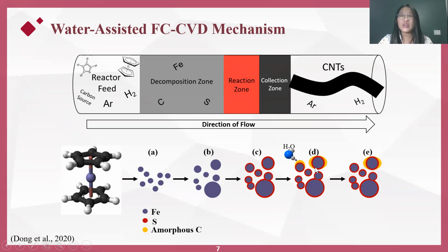Amorphous carbon, as shown in yellow here, is generally considered a major byproduct in hydrocarbon pyrolysis, and its deposition on the catalyst surface makes the catalyst inactive. When we add water into the system, water selectively reacts with the amorphous carbon and removes the coating to revive the catalyst activity. And this will elevate the synthesis efficiency significantly.